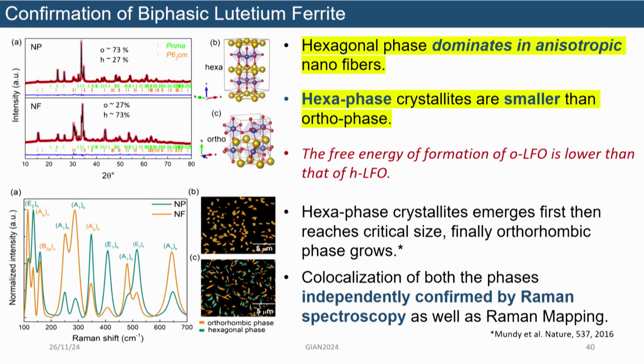So we synthesized them. Then we were trying to find out what structure it is. The structure was supposed to be orthorhombic, but it was not orthorhombic. We were investigating and we were seeing there are a few extra peaks, and we were not able to find out what it is. I was telling my colleague all the time that we need to resynthesize, it is not pure, and we did it 10 times, and every time we got the same result. Later one day we were sitting and matching the peaks, and then we thought, why don't we match it with the hexagonal phase of lutetium orthoferrite, and we did, and everything matched. So there was a combination of orthorhombic and hexagonal in the same material.